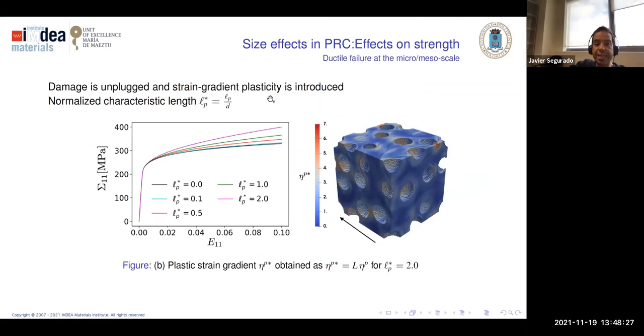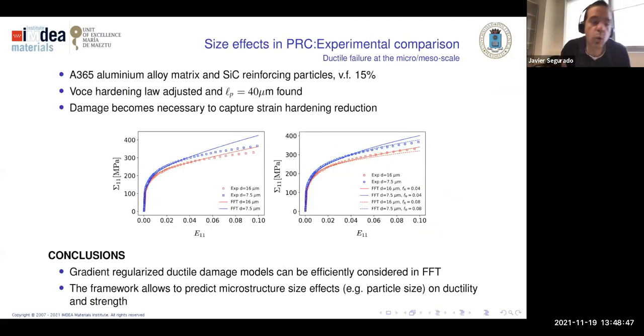We do that including strain gradient plasticity, similar to what I presented at the beginning, together with this damage model, and we see that the smaller the particle, D, smaller meaning L asterisk bigger, the stronger the material, similar to the Hall-Petch relation that we have. And we can see if this goes with the experiments, and more or less it works. So we have taken an experiment with the same material having the same volume fraction, but two different particle sizes, and we see that we can quite accurately predict the size effect on the particle first. And the second thing that we see is that if we don't use damage, we over predict. So when we use both ductile regularized damage plus strain gradient plasticity, we are able to predict accurately the effect of the particle size on the global response.